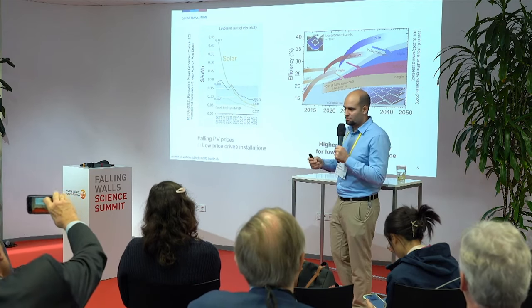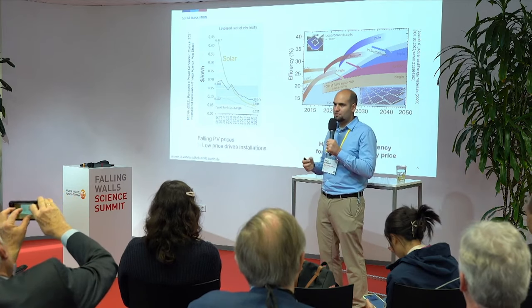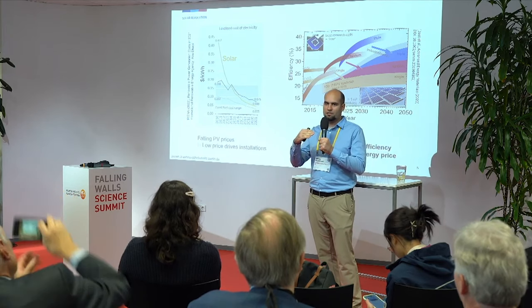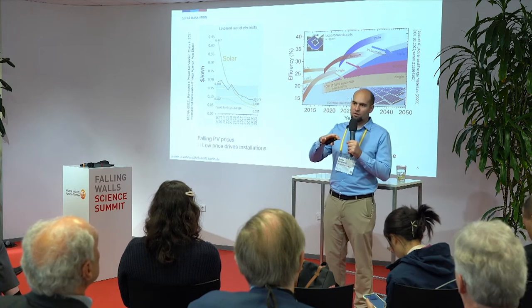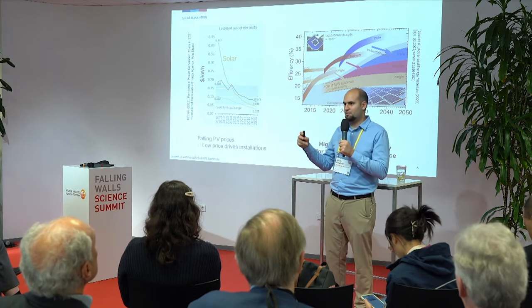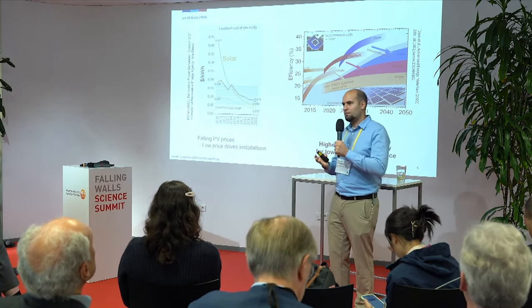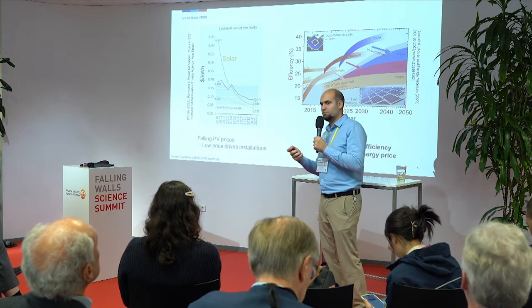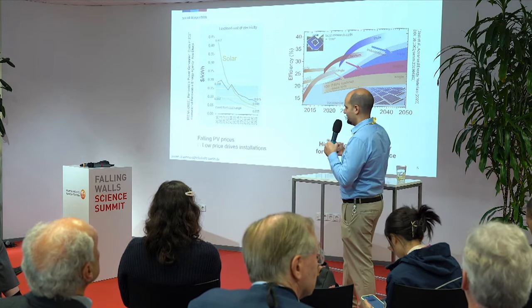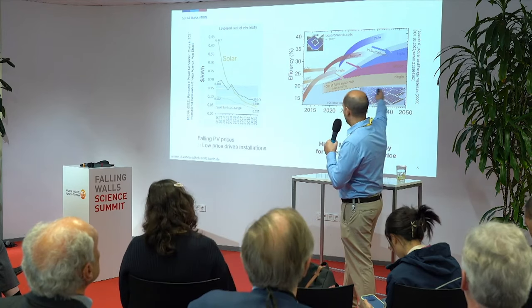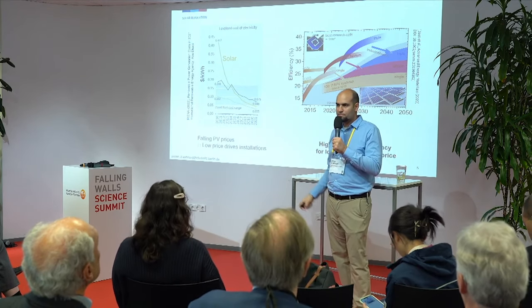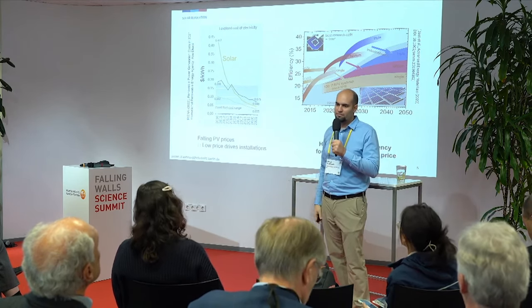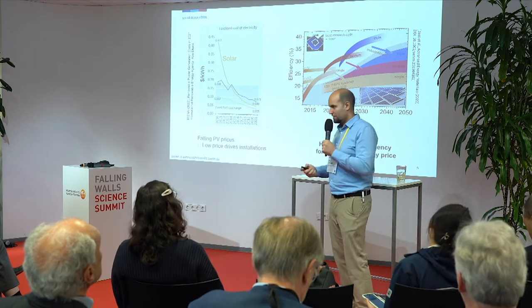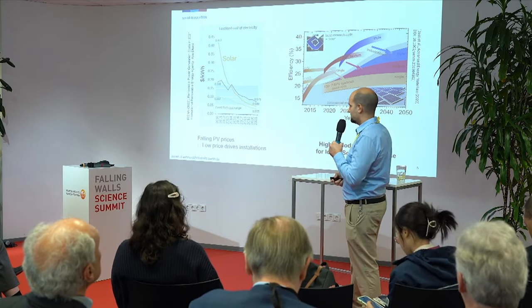There are several ways to do this, and we think the most promising way is to stack solar cell materials on top of each other that are optimized to convert different parts of the solar spectrum as efficiently as possible and to work together, basically. So, for example, when you stack two cells, you would have a tandem solar cell, which then can reach efficiencies of over 30%, or a triple solar cell going to 35%, realistically. This is what we pursue at Helmholtz Zentrum Berlin.